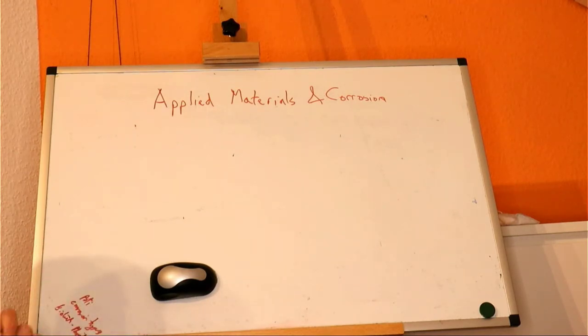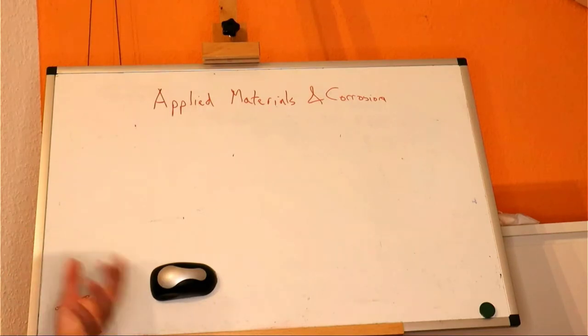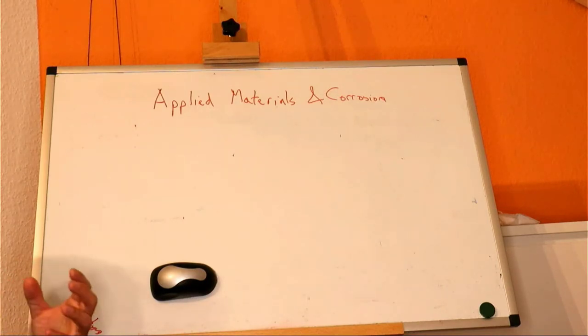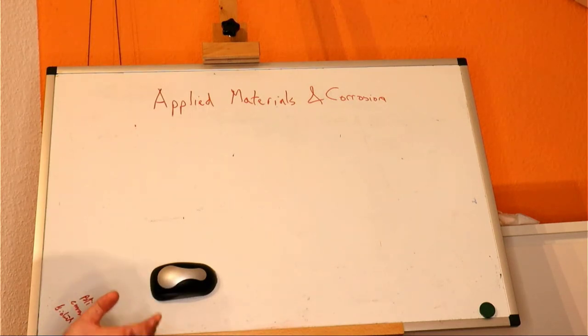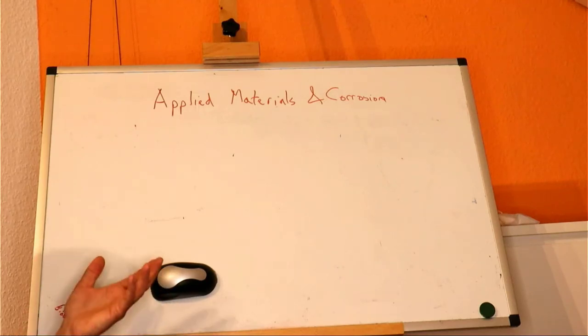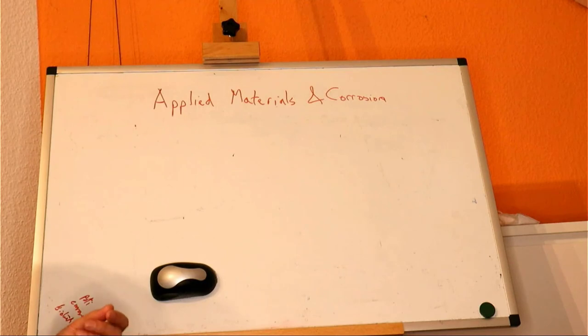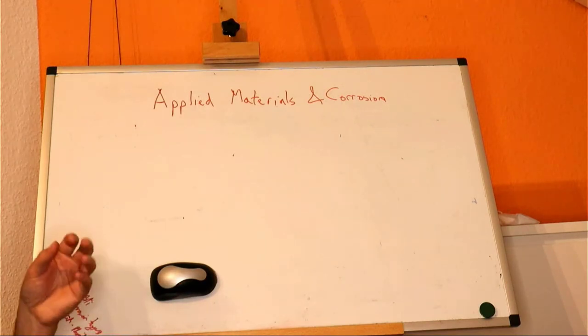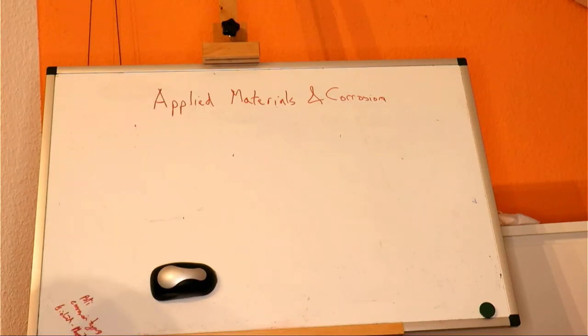I've got some paint which is really terrible, which is obviously good for this particular application because then it falls off easily. What is interesting about it is that it reminds us how poor a resistor to oxygen polymers are. Oxygen typically goes through polymers pretty fast, and even though polymers are pretty good against water, a little bit of water vapor makes it through eventually and will get to the other side. Even in a very good, a very resistant polymer like epoxy, a small amount of moisture will make it to the surface eventually, and it's pretty much impossible to prevent that from happening.